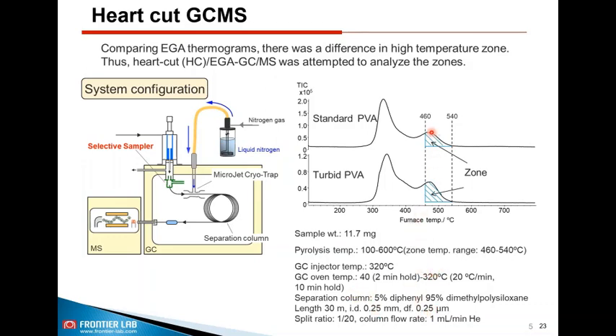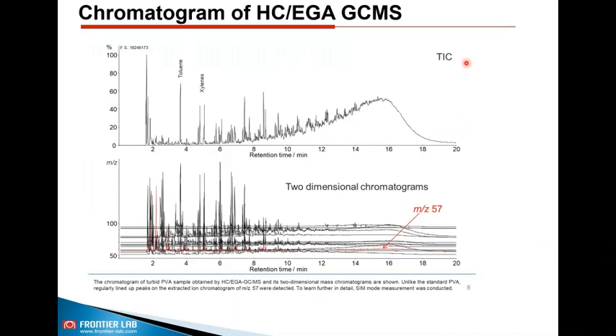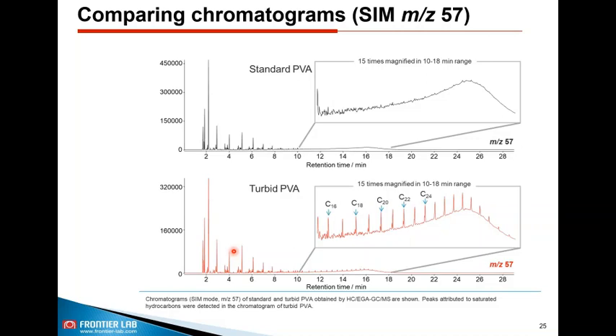So what we are doing is we are collecting the fraction that is evolved from 460 degree to 540 degree. Then this fraction is being analyzed by the GC, and this is the total ion chromatogram, and this is the extracted ion chromatogram, where we see there is one kind of extra peak that is seen in the turbid or the failed PVA, polyvinyl alcohol. Then we have zoomed further by using the SIM mode. In this SIM mode, we could see that this extra peak coming due to mass charge ratio of 57 is seen only in turbid polyvinyl alcohol, but not in the other. So we can say in a way, this is the one that could be a reason for this turbidity.